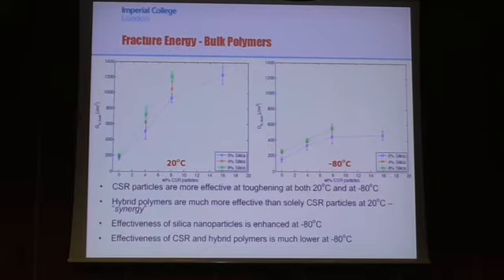When we go to minus 80 degrees, the first thing that we can notice is that adding the silica actually seems to have a beneficial effect.